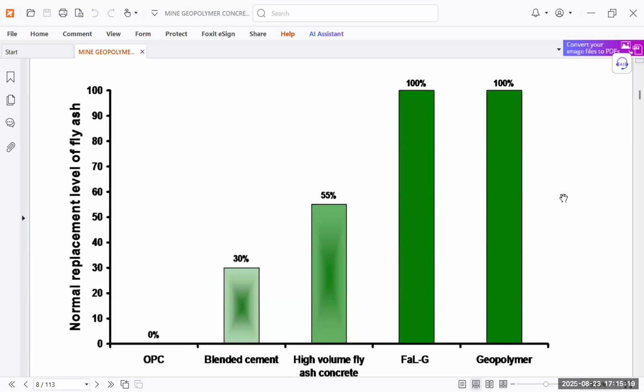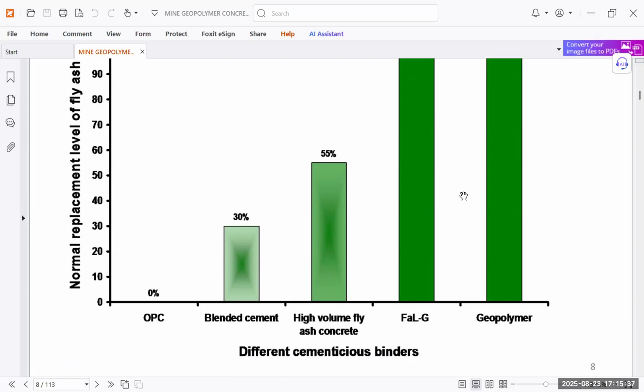With geopolymer, a 100% replacement can be done. And you can see the OPC is normal, not blended cement. We are replacing by 30% with blended cement, 55% with high volume fly ash concrete, and 100% with FaL-G and geopolymer also 100%. So we want to reduce this CO2 emission part by replacing OPC using geopolymer concrete.